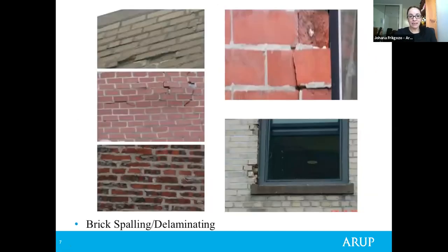Brick spalling and delamination usually manifests in the outer surface of the masonry wall splitting apart. There is an uneven break of the outer face. Usually some bricks have already detached or are about to fall. The probable causes: it's more common in glazed brick and coated brick, where migration of water out of the brick unit is severely blocked by lack of permeability of the outer layer.